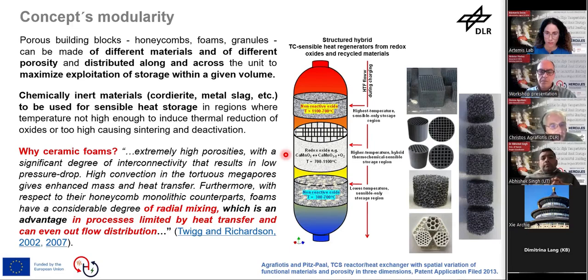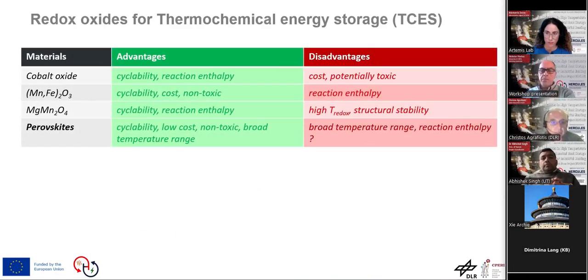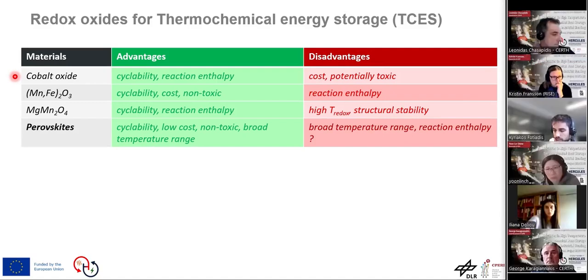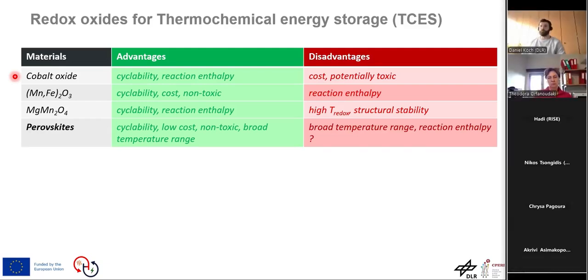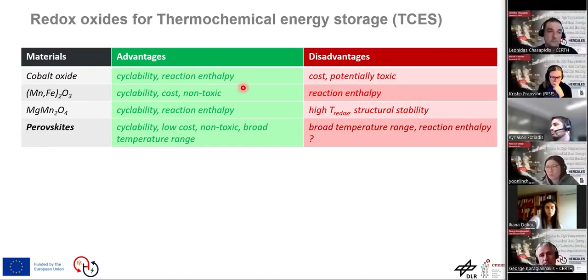If we click on the next slide, we will see, okay, we want to make these porous honeycombs. Out of which materials? There are several kinds of oxides that operate via this cyclic redox scheme that Abhishek showed before. One family is the cobalt oxide. You see with green the advantages and with red the disadvantages. Cobalt oxide has been used a lot as a model material because it's very reliable, cyclable. It has a very high reaction enthalpy and can operate for many, many cycles constantly. But on the other hand, it has high cost and potentially is considered toxic.